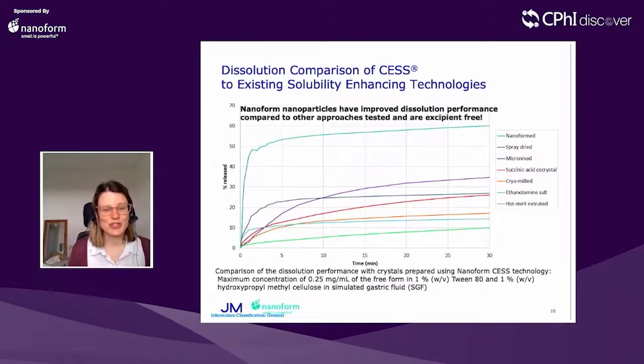So finally came the dissolution comparison of Nanoform's nanoized particles with the different crystal and particle engineered materials that we'd generated in the study. So here we'd generated a dissolution method where we were looking at analysing the initial dissolution rate of those different materials. And we wanted to make sure that method was suitable for a whole range of dissolution profiles and material behaviours. So we used simulated gastric fluid as a media and with Tween and HPMC to make sure we got a good proper dispersion of all those different materials. And I think the results here speak for themselves.